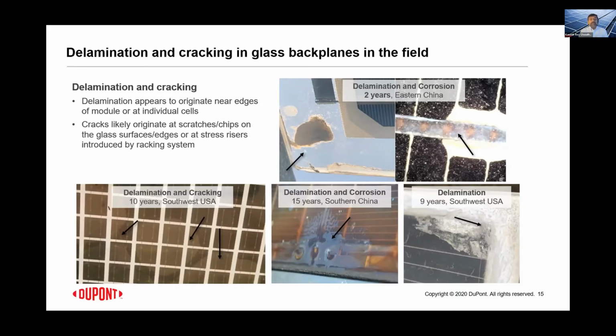We have seen delamination, typically originating from the edges and then working its way through. And once the delamination starts, it forms a pathway for other things to get in, leading to corrosion and other things. The other issue is cracking. Typically, cracks originate at scratches or chips on the glass surface, and then they start propagating.